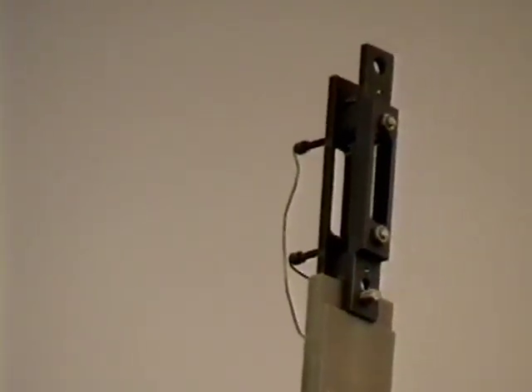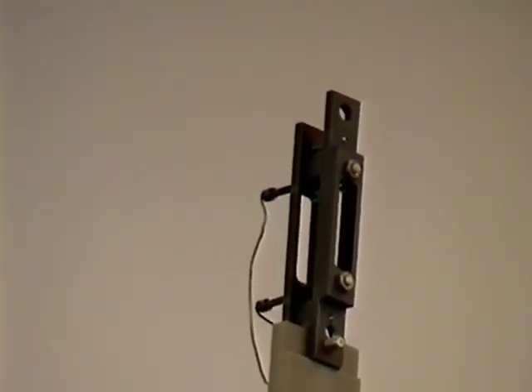Okay, this is the handle for the sample. In this case, there is a new sample. I showed the old one. The new sample is just a small rod of silicon covered with the layers I mentioned. And in this case, we have palladium on top of this. I'm going to use palladium inside the chamber to load it with hydrogen gas.